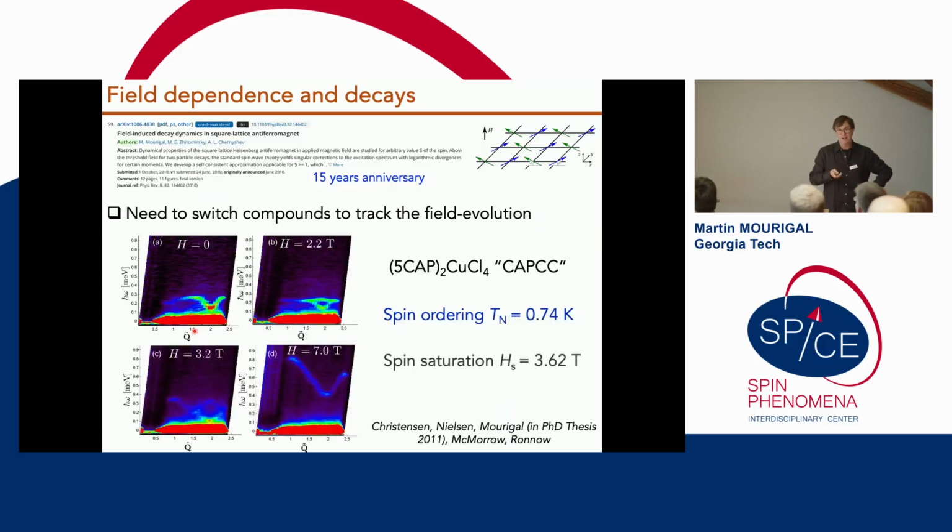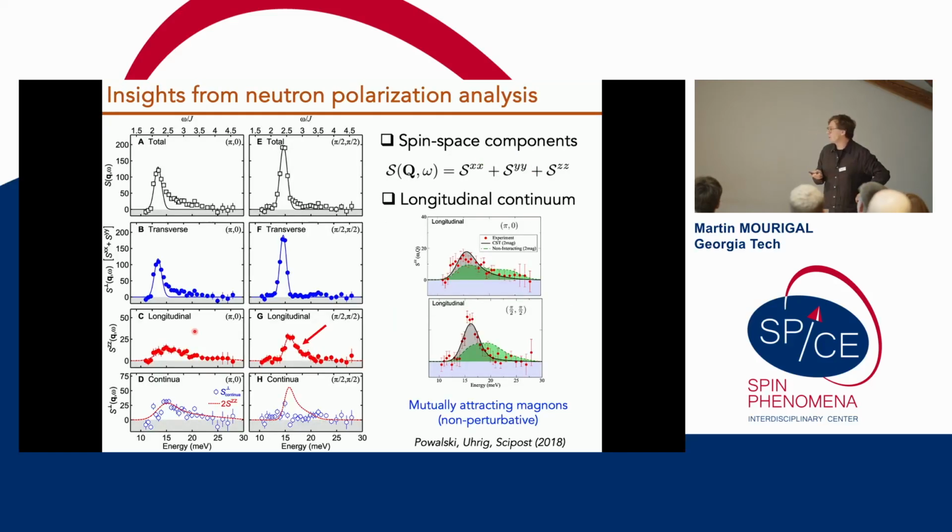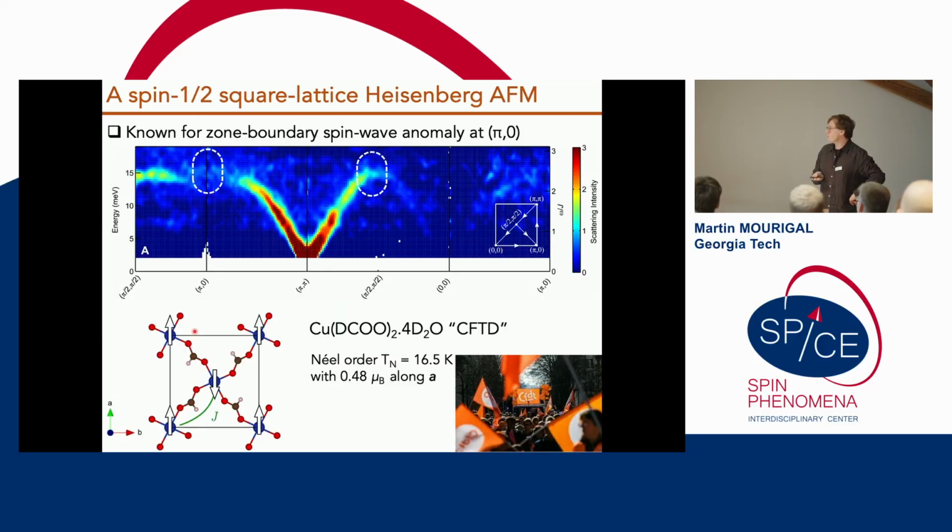How do you know the models are Heisenberg for CFTD and that other one? That's a good question. For CFTD, the symmetry is actually low. There's actually this DM interaction. There are some quite nice ESR measurements from a long time ago that put some limits on the DM, I think at the level of 1%.